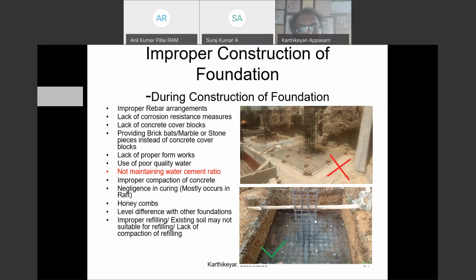And use proper thickness of cover blocks like this. If it is a foundation bottom, where the PCC is provided, you have to use 50 mm cover blocks, and the side is 75 mm cover. So use proper cover blocks. Avoid these types of bricks, bats, or other materials, and not properly compacting.